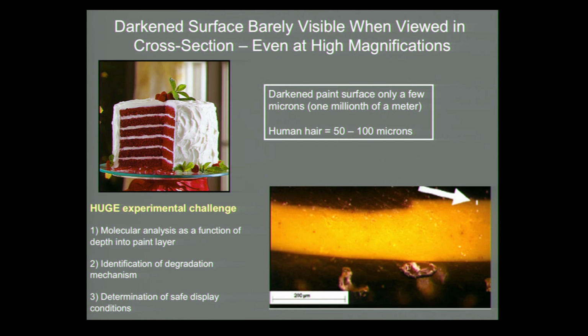And so what we're looking at here is a very large piece of cake, but also a huge experimental challenge, because we need to do molecular analysis as a function of depth into the paint layer, and we need to use that information in order to identify the degradation mechanism. And then also, once we identify the degradation mechanism, then we can determine the safe display conditions for the painting.